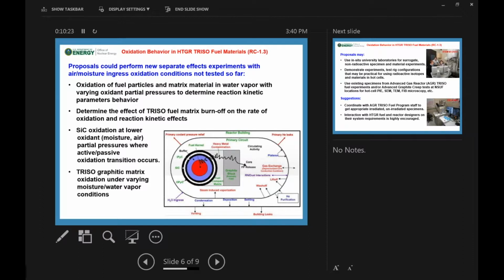So what kinds of proposals could you do? I give this figure at the bottom where we have the kernel. It's basically, obviously not to scale, but there's different ways that fission products can be released. There's heavy metal contamination that might be picked up as we compact. You know, a particle might be broken and we might pick up some tramp uranium. We have contamination that can happen inside the block as well. But the main thing here is that we have different ways of having fission products move and be transported back and forth into the system. So water ingress, air ingress, primary coolant helium leaks leave our particles vulnerable to corrosion.